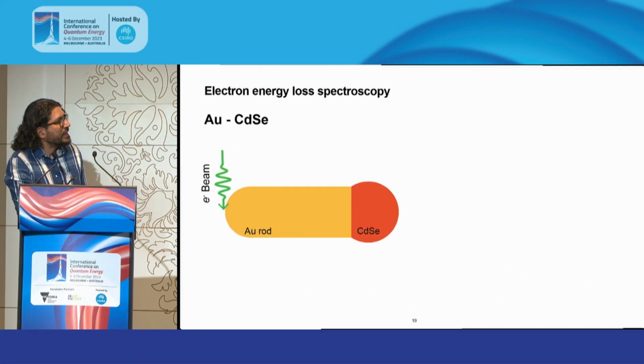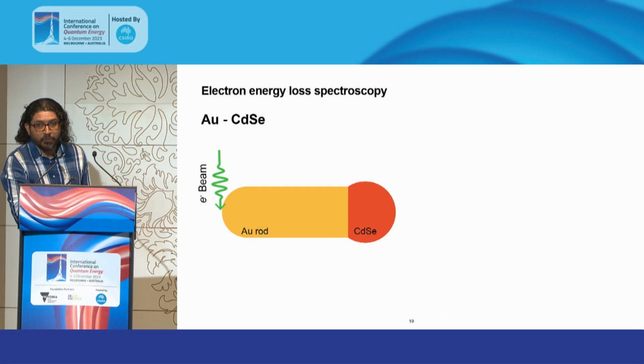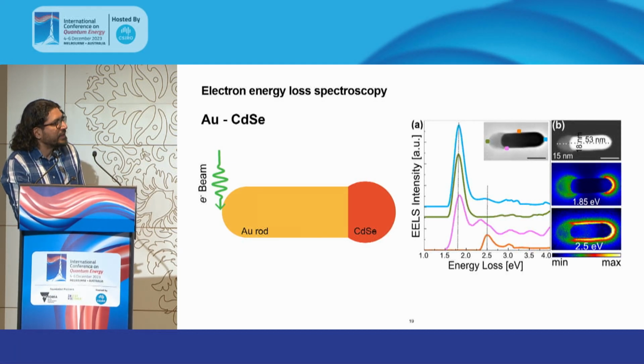All right, now we grow the cadmium selenide quantum dots on the particles, and we repeat the experiment. Again, this is what the data looks like. Contrary to the bare rod or the metal nanorod results, we see here that there is more intensity of the signals at the end where we have the metal alone, and there is, by comparison, a strong damping of the oscillation near the quantum dot region of the maps here.